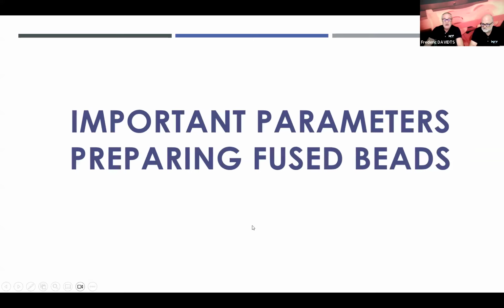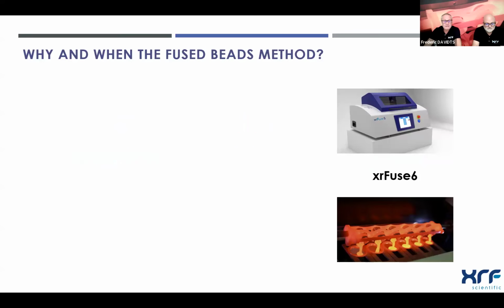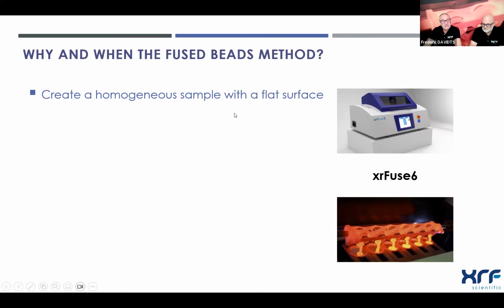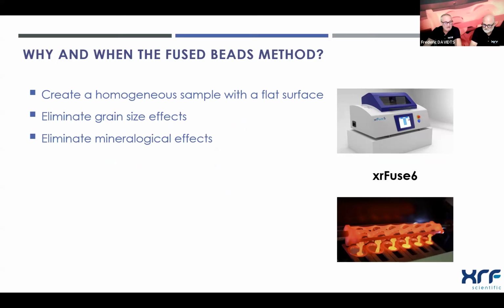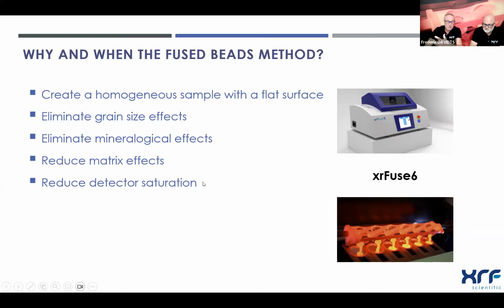And it is always good that the sample that we prepare can be reused over a longer period of time. Now, what are important parameters when we talk about the fused beads sample preparation? Well, first of all, we need decent devices. You can see here the XR Fuse 6, which is a 6-position fused bead machine, so you can prepare 6 samples simultaneously. And as mentioned before, we want to have these samples very homogeneous and with a flat surface. We want to eliminate grain size effects and mineralogical effects. We also want to reduce matrix effects and detector saturation. Sometimes you have samples like an iron ore or a copper ore that may have a very high concentration of the respective elements that saturate your detector. By diluting it, making fused beads, we can reduce this.